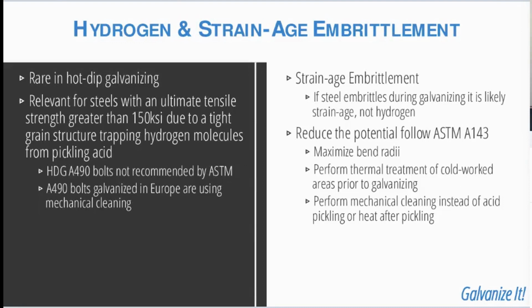On the other hand, hydrogen embrittlement could occasionally be the culprit, but not typically unless galvanizing materials with ultimate tensile strengths above 170 KSI, or any material with a very tight grain structure, which could entrap hydrogen from the pickling process used in the galvanizing pretreatment. Generally speaking, hydrogen embrittlement is not a concern for typical products to be galvanized. But for steels that are above 170 KSI ultimate tensile strength, this is where we would investigate alternative cleaning methods that can be used. And that is what's used to galvanize these articles overseas.